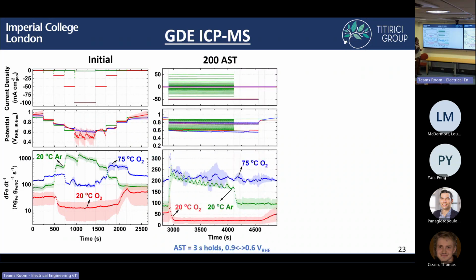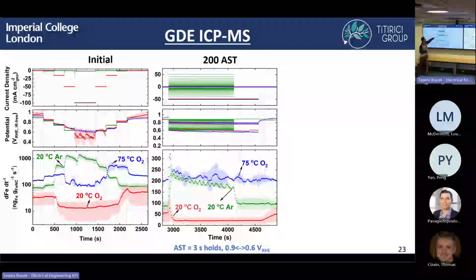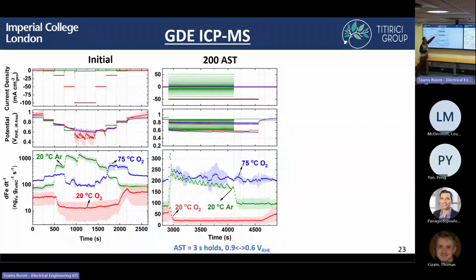And then looking at the 200 accelerated stress tests. So in all the measurements, we're stepping from 0.9 to 0.6 volts. In argon, we're getting high current, but this is just pseudo-capacitance. There's no oxygen reduction taking place. Whereas in oxygen, we see that we have constant minus 50 milliamp per centimeter squared, and this is coming from oxygen conversion to water. And so again, we see some very stark differences between the three different measurements.